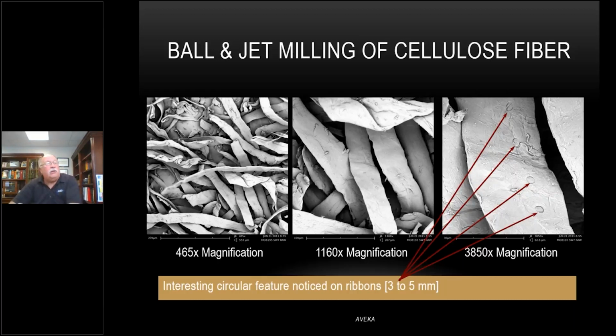So the pictures that we have here show cellulose, dried cellulose fiber. This is wood pulp cellulose. And just for those of you that don't know the structure of cellulose, and this is important to know, cellulose is typically a tube. This is where the water flows up in a plant, whether it's wood or a vegetable type plant. And these things are hollow, and the walls of the fiber themselves actually are like a belted bias tire, where there's multiple microfibrils of cellulose that form this structure. And so it basically looks like a bias belted tire.